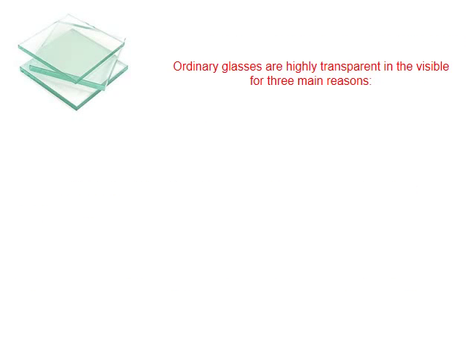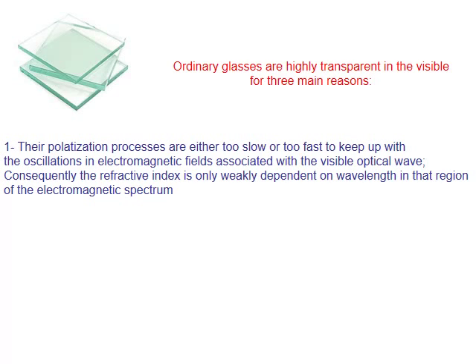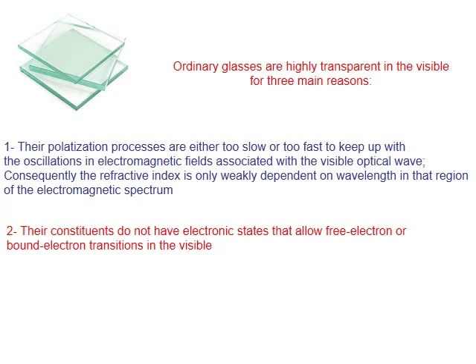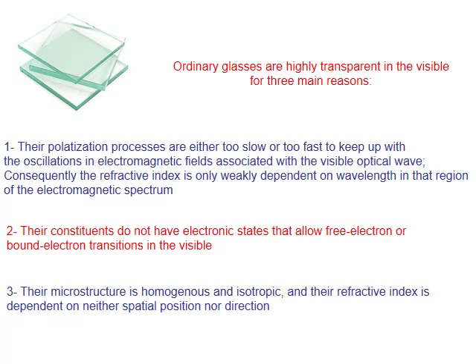Ordinary glasses are highly transparent in the visible for three main reasons. 1. Their polarization processes are either too slow or too fast to keep up with the oscillations in electromagnetic fields associated with the visible optical wave. Consequently, the refractive index is only weakly dependent on wavelength in that region of the electromagnetic spectrum. 2. Their constituents do not have electronic states that allow free electron or bound electron transitions in the visible. And 3. Their microstructure is homogeneous and isotropic, and their refractive index is dependent on neither spatial position nor direction.